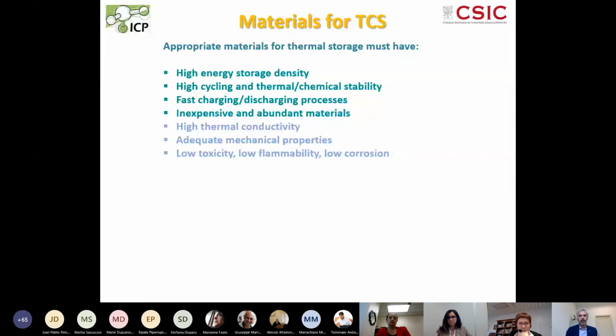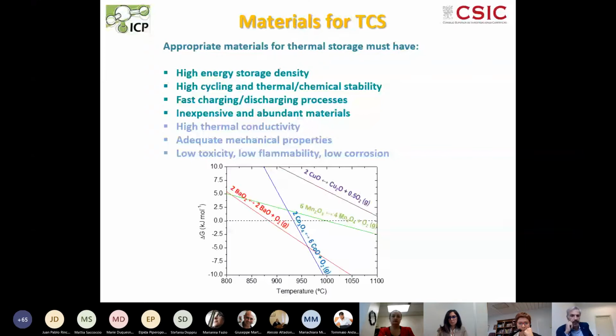for the thermochemical storage. So what do we need for a material to be good for this application? Well, obviously we need a high energy storage density. We need stability, chemical and thermal. We need a rapid kinetic, so we need a fast charging and discharging. And because we are going to use a huge amount of material, several tons, we need something that is cheap and abundant. And if possible, we would also like to have some high thermal conductivity, some good mechanical properties, low toxicity, low flammability, low corrosion, etc.